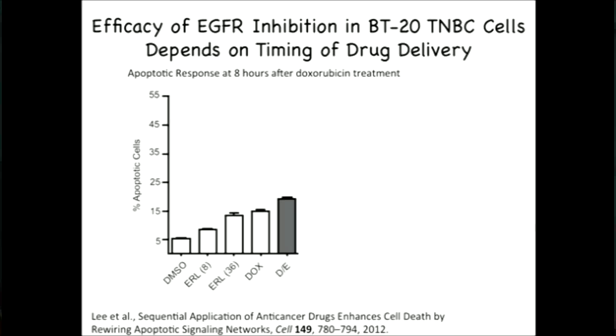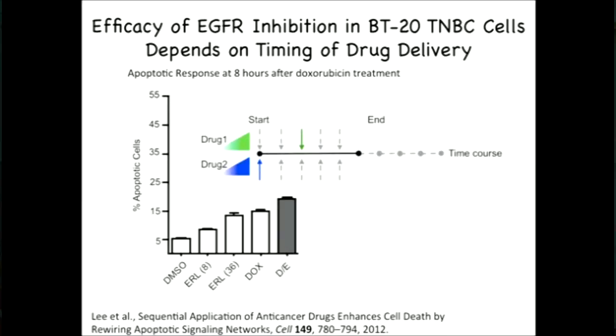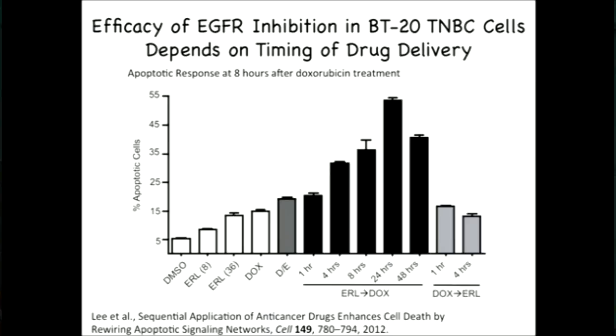He actually uses a drug for this. He can inhibit it in the presence of doxorubicin and see very little impact of combining them. So here you can see doxorubicin combined with this other drug, erlotinib, it doesn't give you very much bang for your buck in terms of killing these tumor cells. However, he found that if he waited and instead of delivering them both at once, he allowed several hours to pass, cell death increased by huge amounts. So you can see here that if you wait 8 hours or 24 hours, you can get a huge difference in the number of cells that die.